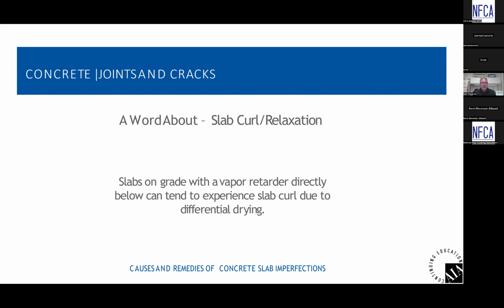So the bottom line here, concrete slabs that are on ground with a vapor retarder directly underneath them can experience slab curl due to differential drying. And what I mean by that is if you have a vapor retarder under the slab, which is recommended for any moisture sensitive flooring that's going to go on that concrete, the mixed water in the concrete, that 65% of the mixed water that evaporates out, is not going to go down. It only goes up.